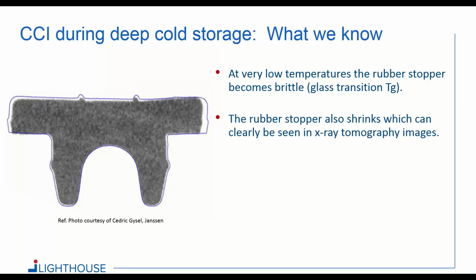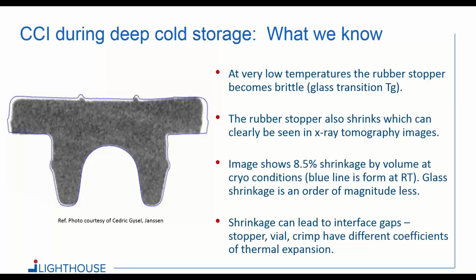What you see here is an image that has a blue outline. That's the outline or form of the rubber stopper at room temperature. And then the gray image that you see is that same stopper, but now at, in this case, cryo temperatures. In this particular case, for this specific stopper, it showed that this stopper shrunk by about 8.5% by volume at cryo conditions. What's interesting is that a glass vial will shrink an order of magnitude less at these same conditions. So the conclusion is that this shrinkage can lead to interface gaps. Wherever you have the stopper, the vial, or the crimp interfacing with each other, they're all made of different materials: a rubber stopper, a glass vial, a metal crimp. These materials all have different coefficients of thermal expansion, which means that they will shrink at different rates.